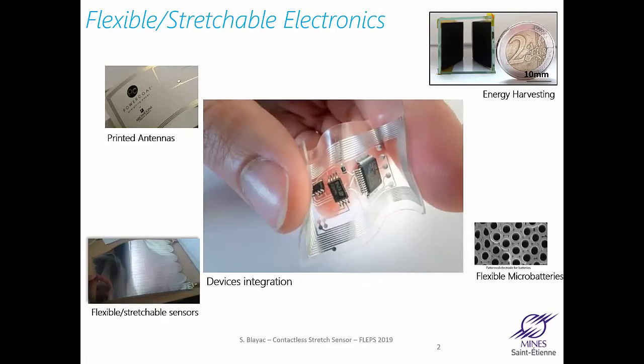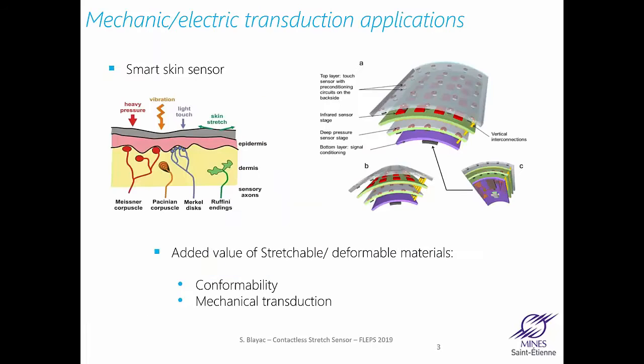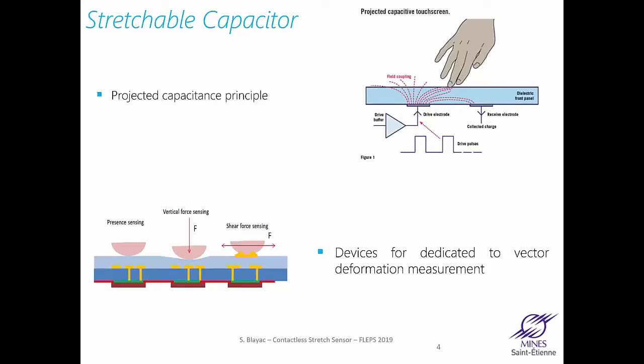Once all this is done, we integrate this in flexible or stretchable substrates. So to go to the sensor aspects, if we start from a given application like a smart skin, the interesting thing in stretchable materials is that you have a natural transduction of pressure, of any mechanical solicitation, into a deformation of the material. And that's interesting to exploit this stretchability, the softness of the material, to fabricate sensors. So starting from this, we can then design some sensors that are derived from the principle of projected capacitance, the classical sensor that we have on our smartphones, for example, where you have two electrodes, you have some field lines between the electrodes, and putting something in the field of the field lines will change the capacitance.